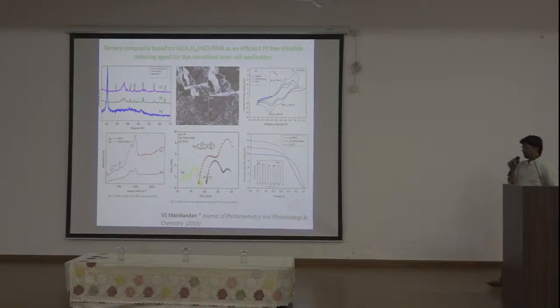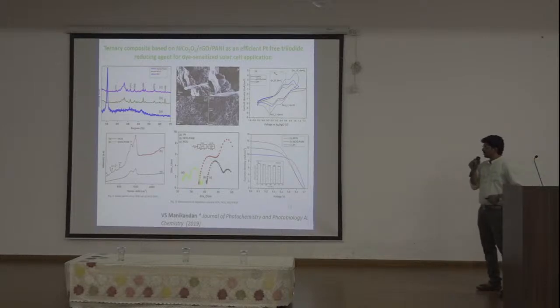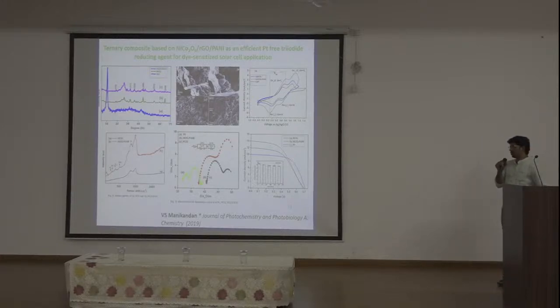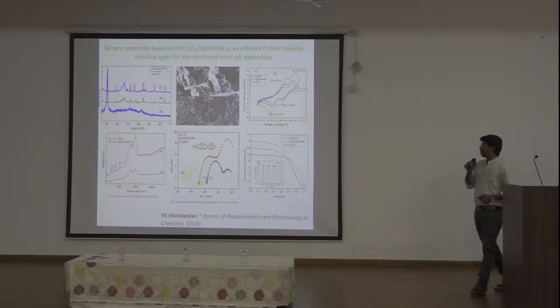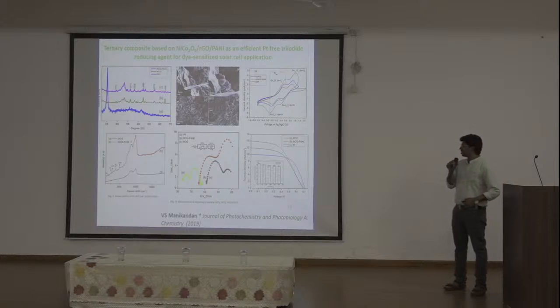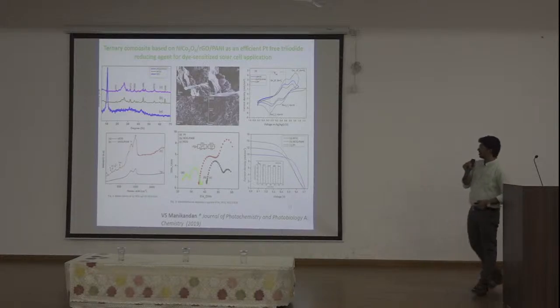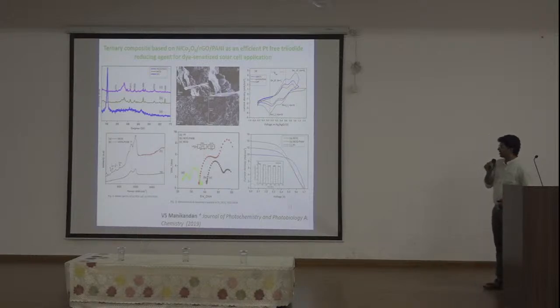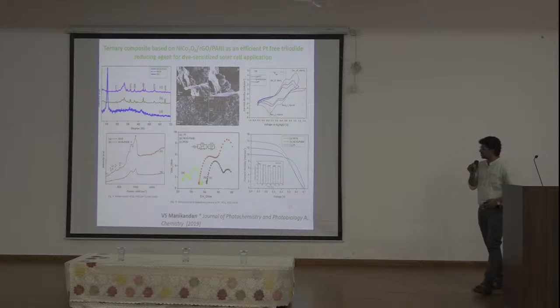From the electrochemical impedance spectra, we can check that over the frequency region, from higher frequency to lower frequency, there are two semicircles. The first semicircle indicates the charge transfer resistance from the counter electrode to the electrolyte. After inclusion of the ternary composite, the charge transfer resistance is decreasing, as we can see in the red color figure, where the radius shows the charge transfer resistance is decreasing.